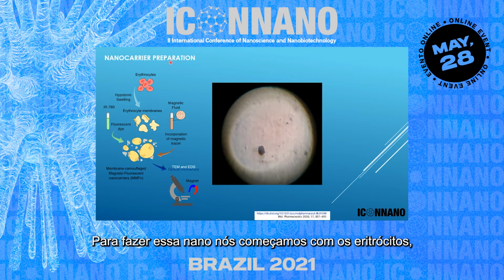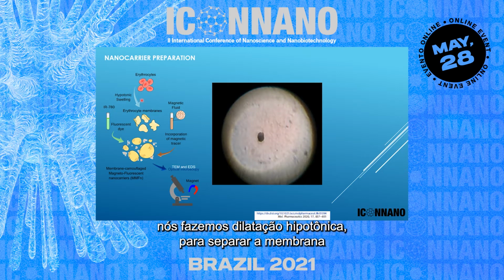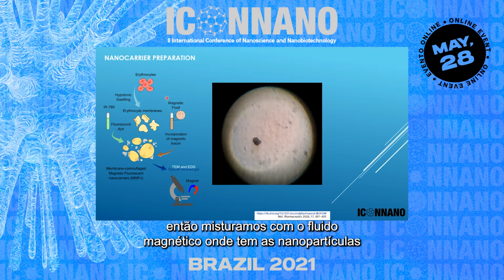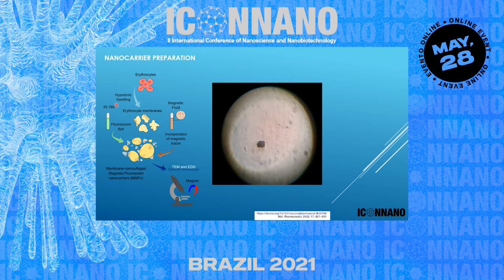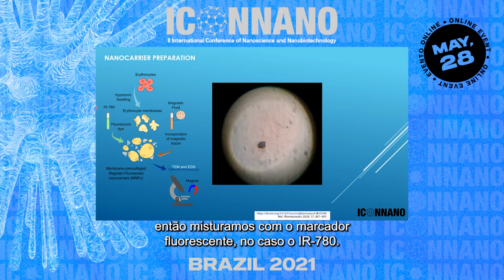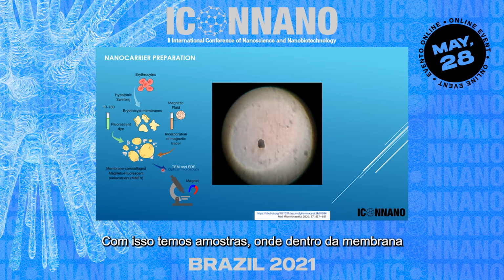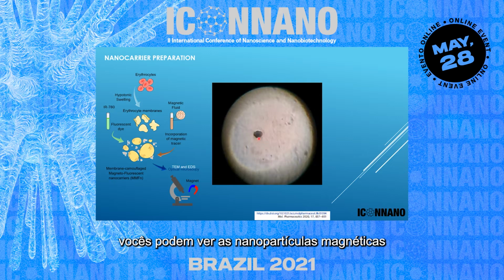Okay, so to make this nanoparticle, we start first with the erythrocytes. We do a hypotonic swelling, so we separate the erythrocyte membranes. We then mix it with the magnetic fluid that has the nanoparticles and the fluorescence dye, which is IR 780. With that, we get a sample where inside the membranes you can see the magnetic nanoparticles.